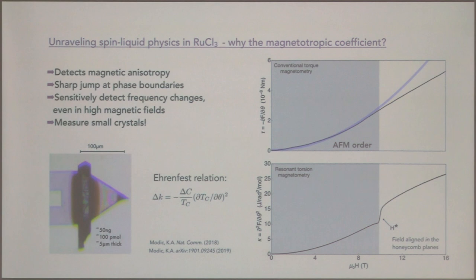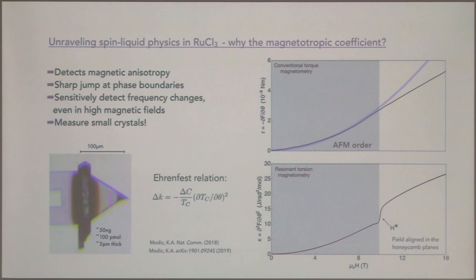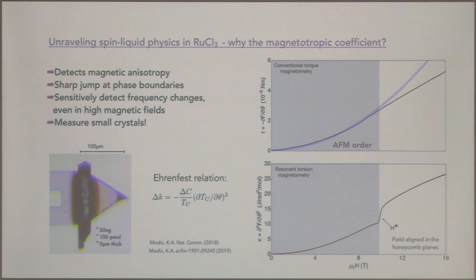The first thing is to convince ourselves we know what we're measuring. The top panel shows a conventional torque measurement with field aligned in the exact same direction — you can see the torque increases quadratically with magnetic field in the antiferromagnetically ordered state, then peels away from that quadratic dependence, marking where you come out of the antiferromagnetic state. With our technique, shown at the bottom, you actually get a very big sharp jump at the phase transition. This technique is ideal for identifying magnetic phase transitions.